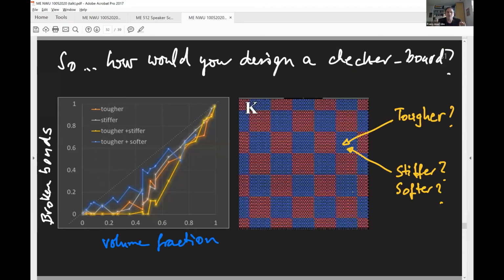Now, this is not only for the checkerboard. You can actually ask yourself, and that's a student problem typically, what would you do? Would you make it tougher, stiffer? You have all these degrees of freedom. Well, here's the same plot which I just showed you, in function of the volume fraction of the blue phase, which is either tougher, or tougher and stiffer, or tougher and softer, right? So which one would you think would make the cut? What is the best material to obtain the maximum toughness? It turns out to be the blue one here, the tougher and softer, tougher and softer than the red phase, because it approaches the upper bound.